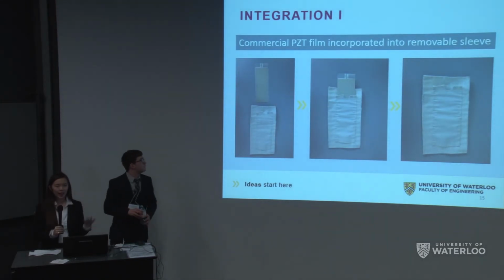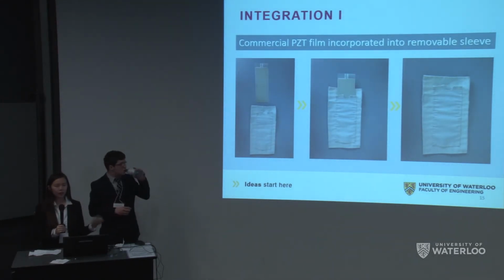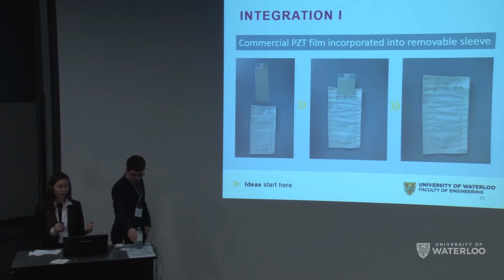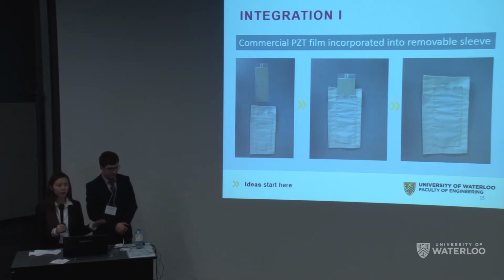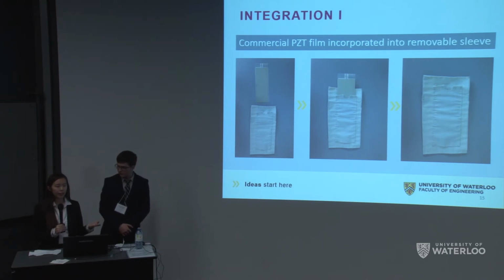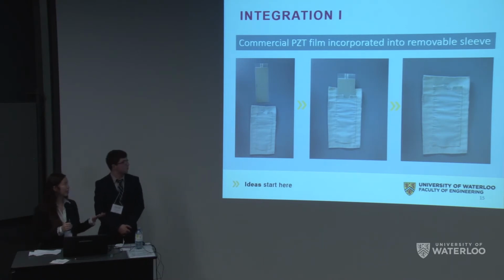So because we couldn't get access to the high voltage lab or any other electrospinner, we decided to focus on the other half of our project, which is essentially showing that we can actually harness the power from a film and translate that into something that could actually power a device. So to do this, we purchased a commercial PZT film and incorporated it into a sleeve. So essentially, we made a sleeve, and the film can be removed from it, which helps us meet our goals of durability, since you would never actually wash the film, so you would avoid mechanical agitation and the water damage